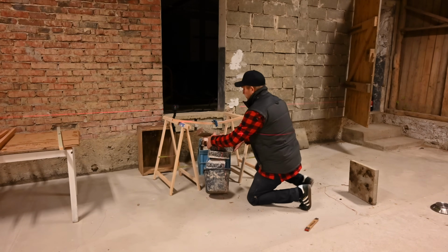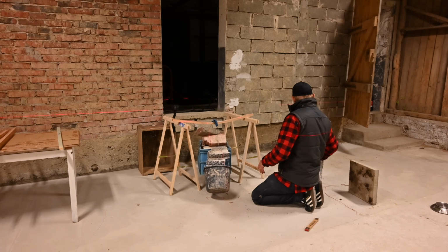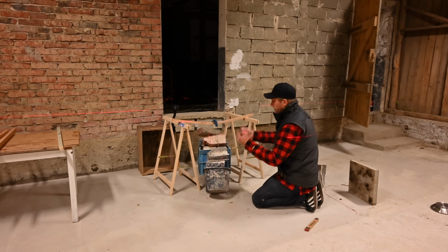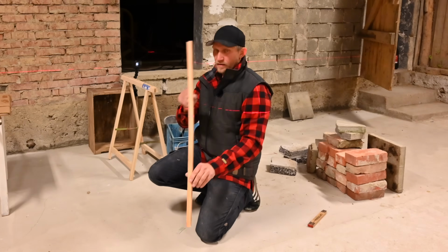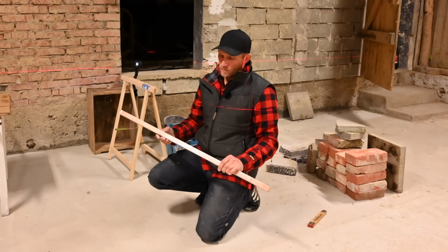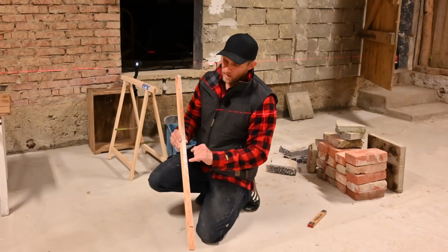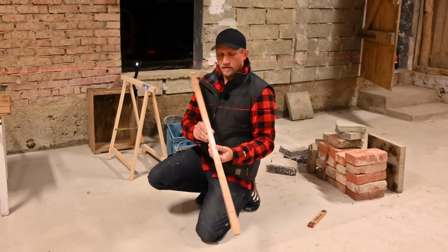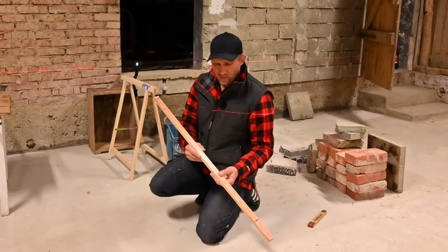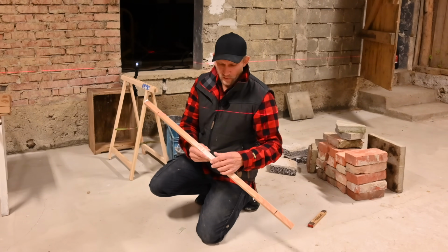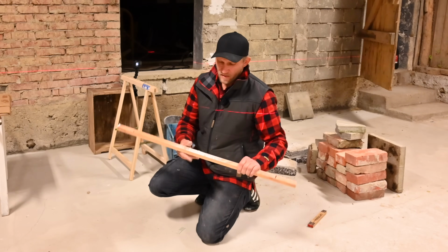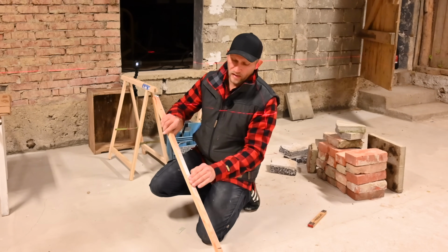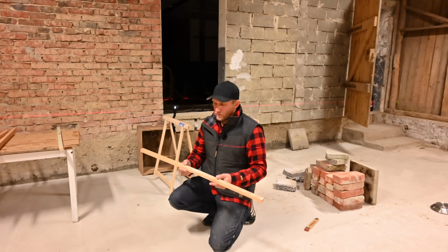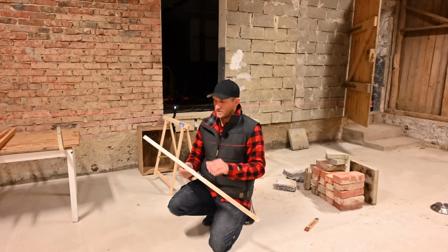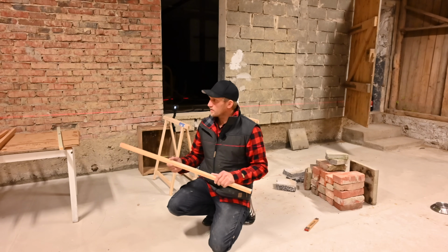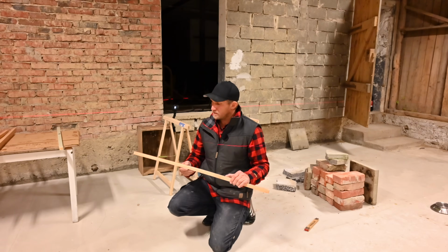So now we'll take the weight off and we'll see if the wood will spring back to its original shape. As you can see, it's almost back into shape. There's some delamination, or I think it's the glass fiber that hasn't come loose from the wood, but something has happened with the glass fiber here on top. So I'll put 100 kilo plus on this sample. I guess a lot of these samples will be that.